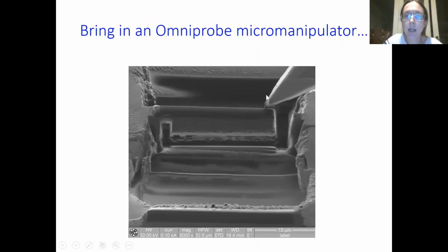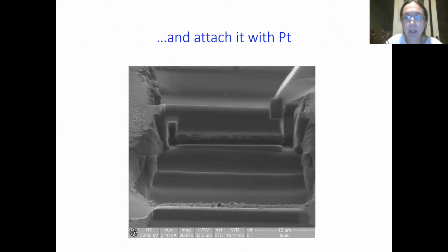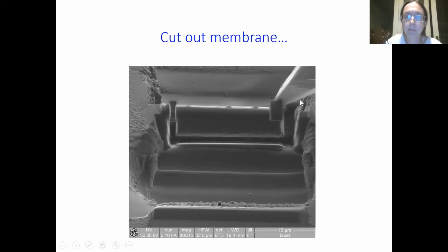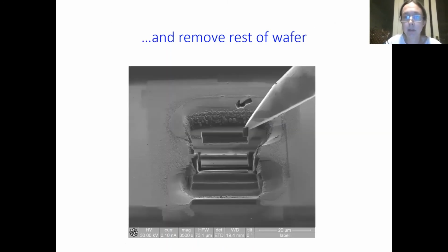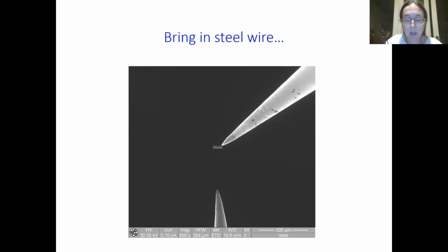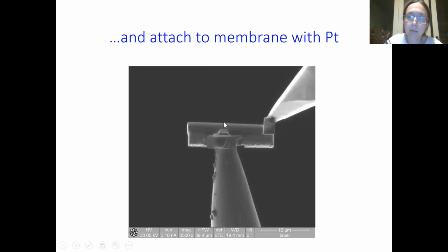We bring in a very sharp needle called an omniprobe micromanipulator, and we use our platinum deposition to literally, like sellotape, basically, the thin foil sample onto the micromanipulator. We chop it free and we bring it away from the wafer. And we're going to put it, in this case, onto a steel post. So here's my membrane, here's my micromanipulator, and there's my steel post.